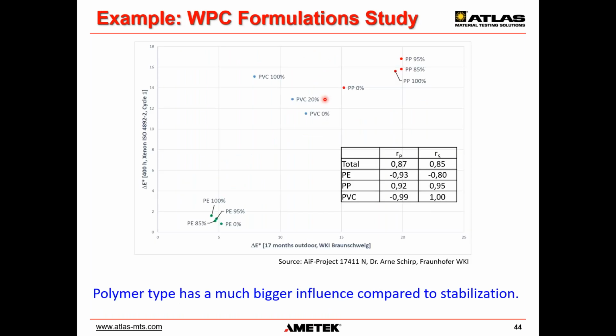And here's also an example for wood plastic composites from a federally funded research project in Germany from the Fraunhofer Institute for Wood Research. They looked at different formulations of wood plastic composites with different amounts of stabilizers. It was relatively interesting that they found overall a good correlation between a xenon arc test according to ISO 4892-2 and outdoor weathering in Braunschweig in Germany. However, the correlation is only good because if you consider all of the materials, they behave completely differently. Polyethylene is much more stable in this study, showing less color change compared to PVC and polypropylene. And so just because you have completely different materials, it shows good correlation.